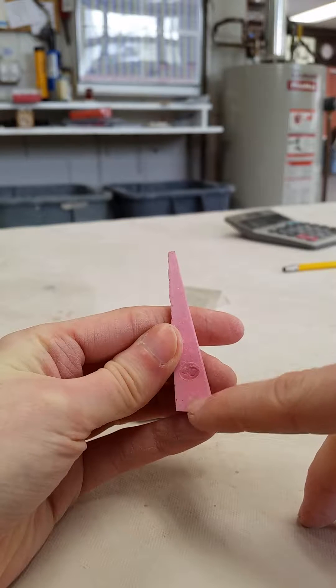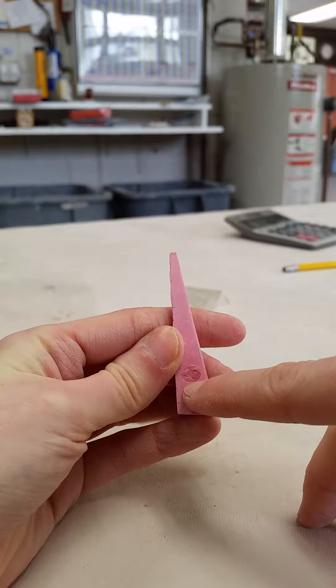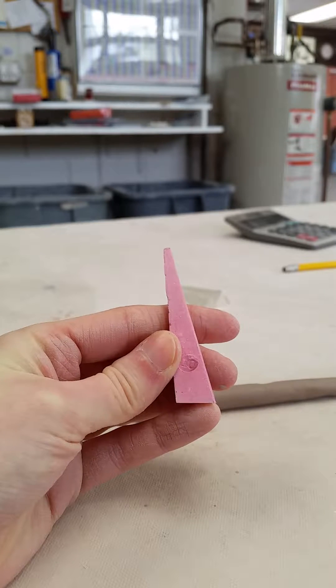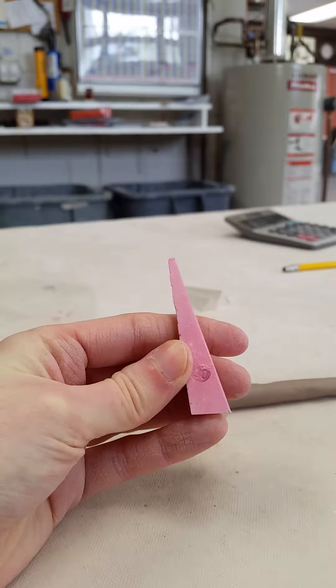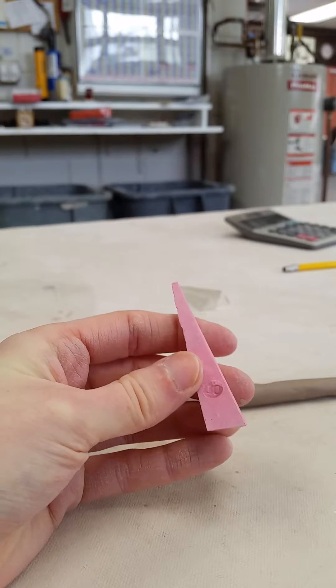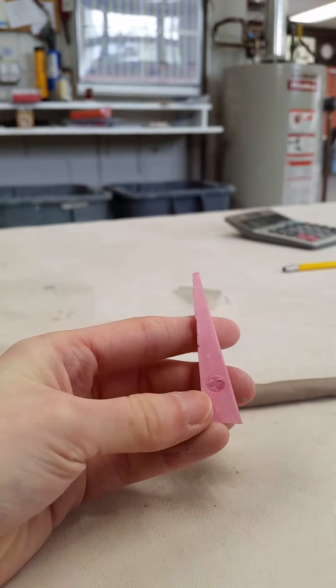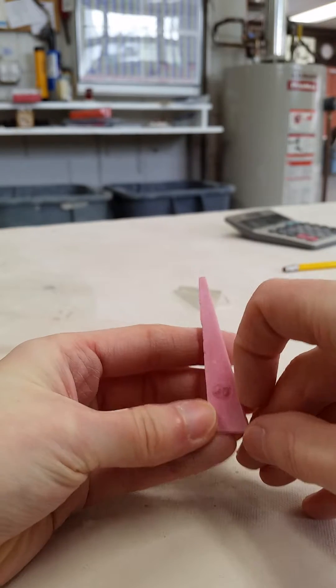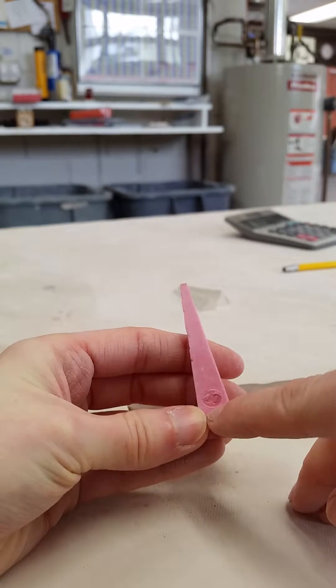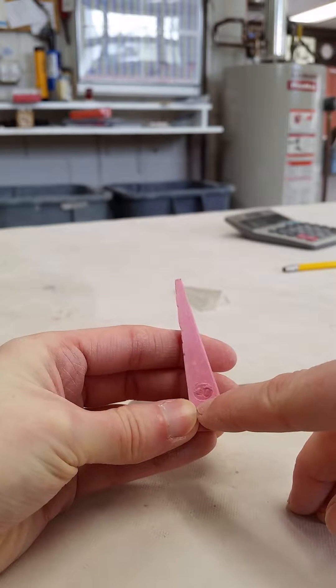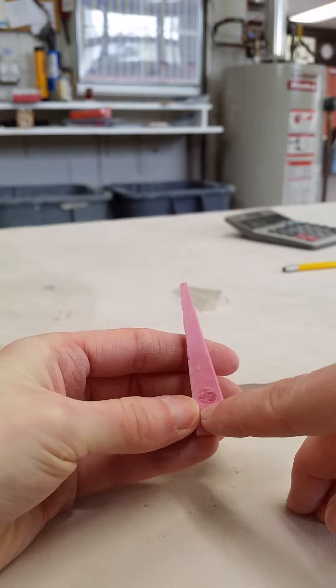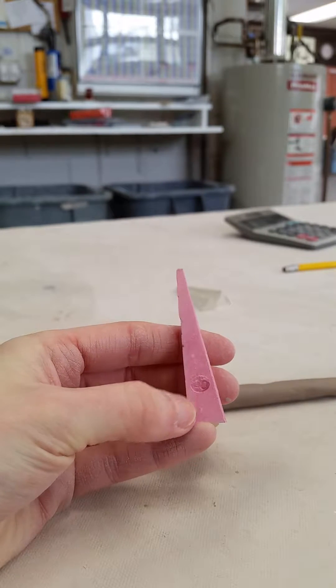To the bottom of this number here, the cone number. If you buy those pre-made cone pack holders that Orton sells, you'll see that the cone will sink up to about half an inch or so, right to the bottom of this number here, which is what they recommend that the cones be mounted in. So I want my coil about that thick.